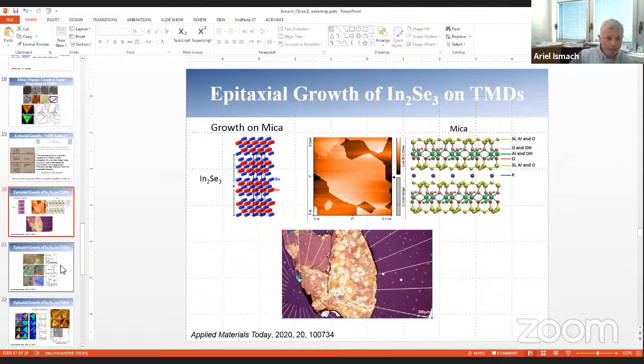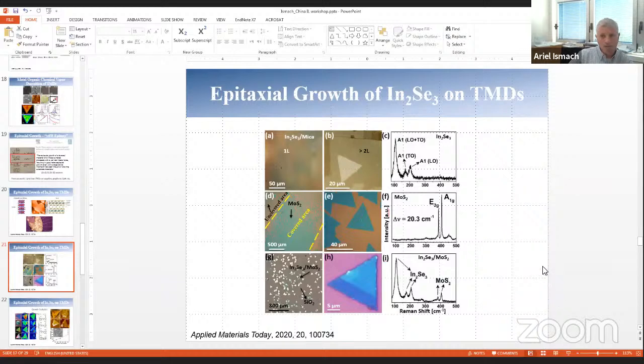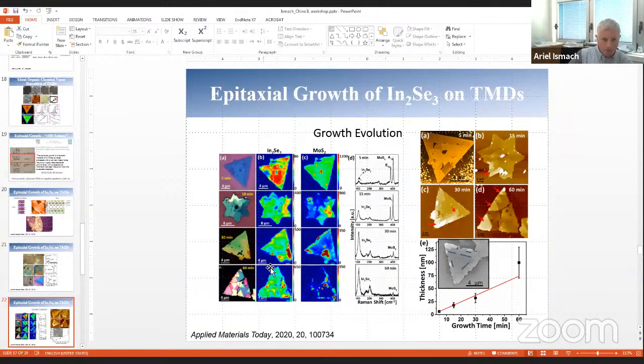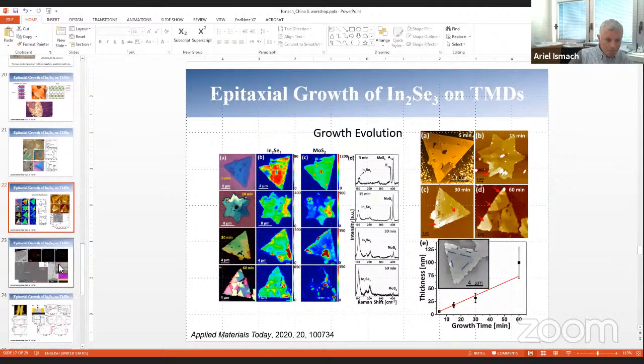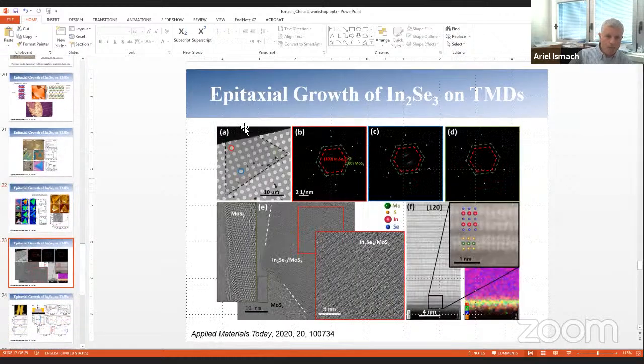Therefore, we implemented an epitaxial growth on TMDs, the same material that I showed you before. We can show that this indium selenide grows very nicely epitaxially on this MoS2. We can show the growth evolution by AFM, Raman, and so on, and we can prove that this is epitaxial growth. Here, this image is a collage of data from 3 different TEMs. So here you can see electron diffraction from different points.